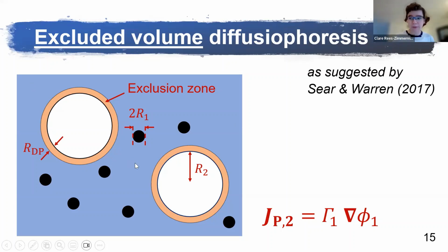By geometry, for hard spheres, we would expect the excluded distance, which I've labeled R_dP, to be equal to R1, the radius of the small particles. But I'm going to explore what happens as R_dP is varied. So that's varying the strength of diffusiophoresis. I include diffusiophoresis in my model by adding another flux term, J, with a diffusiophoretic drift coefficient gamma, and the J is proportional to the concentration gradient of the small particles.